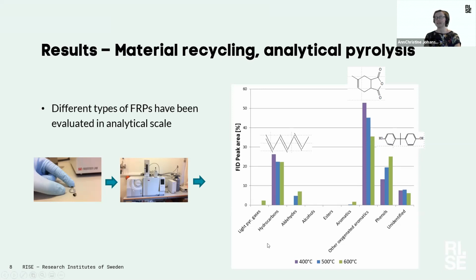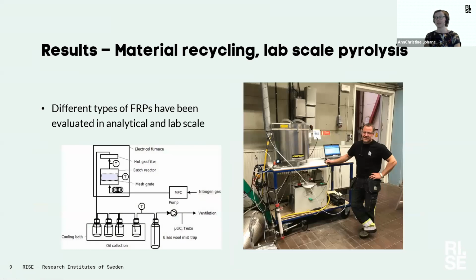And what we see here is actually that the products in the pyrolysis oil, you could say, are very similar to what you put in to produce the composites. So that gives us the possibility that it's actually possible to recover the components in the liquid. We've been going up in scale a bit, working in lab scale. We actually built a small equipment to be able to treat these composites.